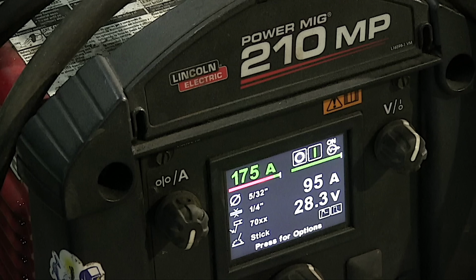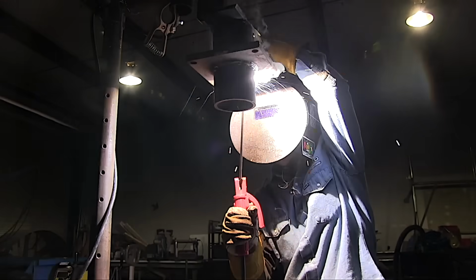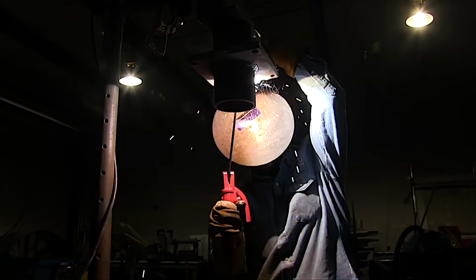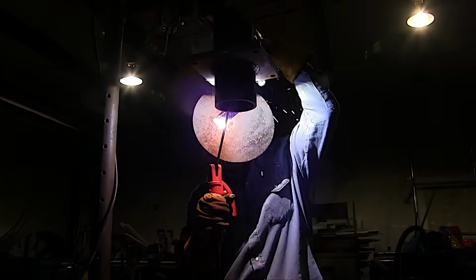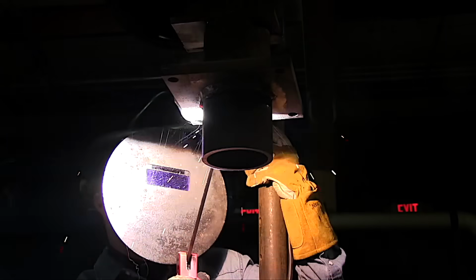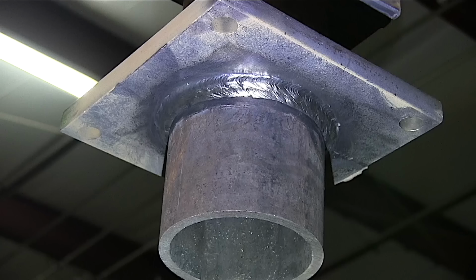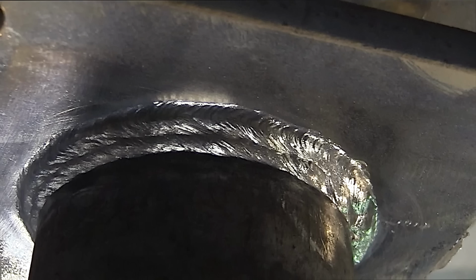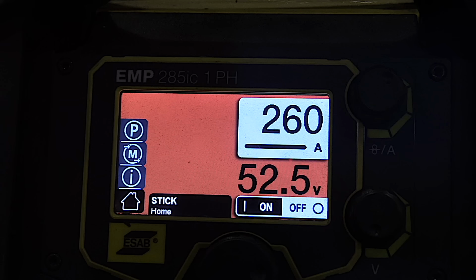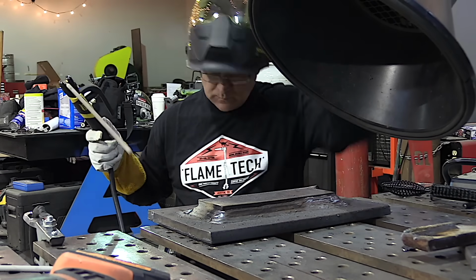Here we're using the 5/32 again, 175 amps because the metal's a little bit thicker. That's a 1-inch thick base plate. But the same things apply whether you're on round or on flat structural shapes. Use a tight arc, don't get carried away with your rod angle, and use enough amperage. Use pretty much the same amperage as you would use for flat and horizontal for overhead, but that's where that tight arc really comes into play. And I can't emphasize it enough. Practice your restarts. You'll always have to make a lot of restarts when you're in tight spots, and being able to make a good restart is huge.